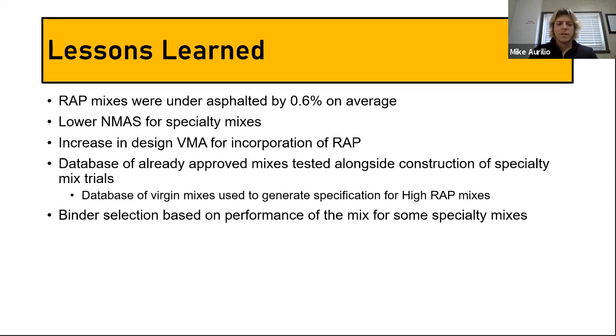All three of these mixes, sorry, technically it's 4 mixes, but 3 of the 4 mixes, the high performance thin overlay, bridge deck course, and the surface course of the high RAP mix were all 9.5 millimeter nominal maximum aggregate size. So they tended to move towards finer graded mixes, partially to move towards higher asphalt cement content. The other nice benefit of using a finer mix is that it's less porous and it's going to reduce the rate of oxidation. Right.